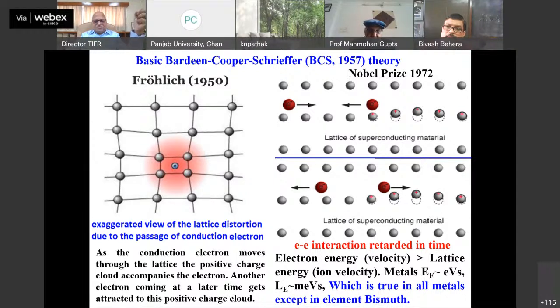So the important consideration there is the electron energy. The velocity of the electrons is about 10 to the power of 4 to 5 times larger than the velocity of the ions. So by the time the electron moves out, the other electron can get attracted to it, which is true for all the metals which you have shown in the periodic table, but not so for bismuth. Bismuth has an electron energy which is comparable to the lattice energy. That's where the problem comes, which I will come to a little later.